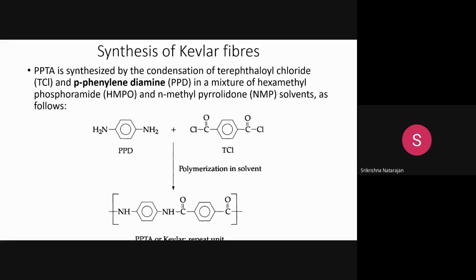A diamine and a diacid, these both are reacted in a mixture of solvents, which are hexamethyl phosphoramide and N-methyl pyrrolidone. You can use the solvents in a mixture, and then you can produce the PPTA, which is the polyparaphenylene. Because of this para position, what happens? It leads to more intermolecular registration. That is why you get good mechanical properties, and it becomes more crystallizable and has high strength and modulus.